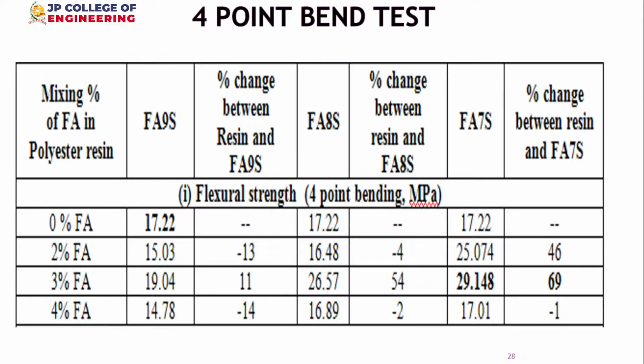Yeah, so then we went for the 4-point bend test, to determine the flexural strength. You can see that the top line, 0%, means pure resin. It has a very low value, 17 MPa, megapascal.